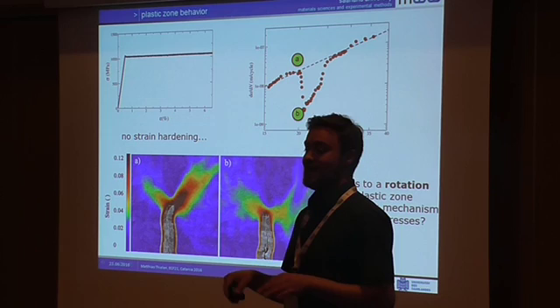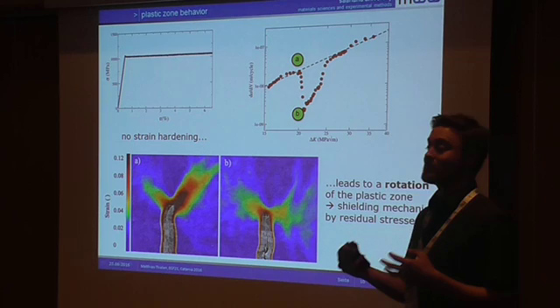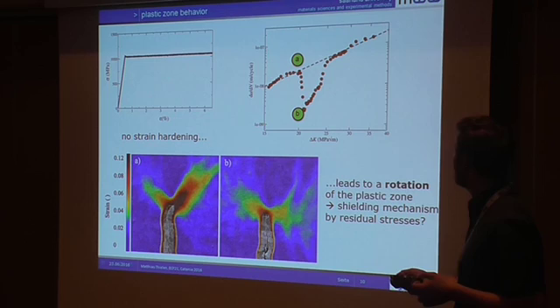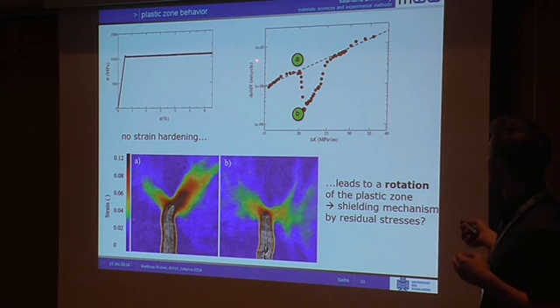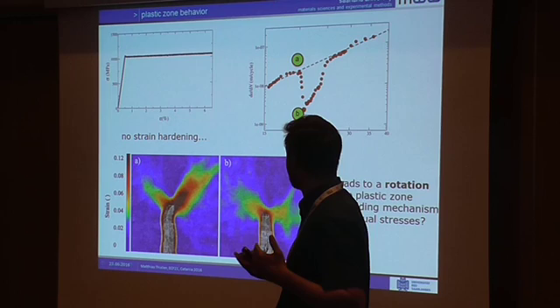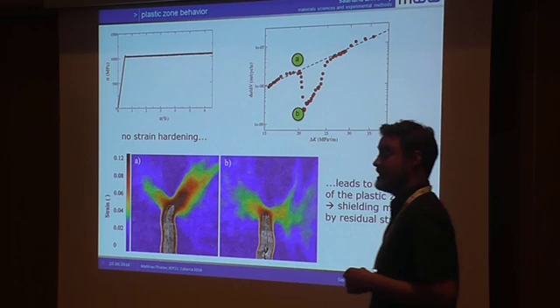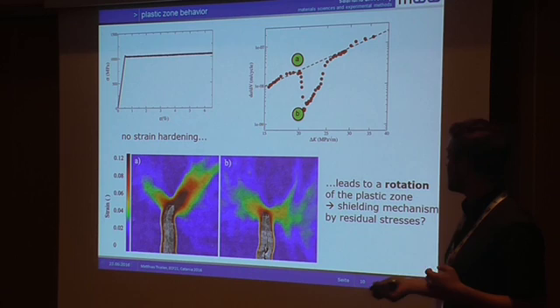If you want to describe material behavior, you start with a simple case — a material that doesn't show any strain hardening behavior. What you would have seen in the video is we let the crack grow to a certain point, then put it into our scanning electron microscope with a small tensile tester. We open the crack, match the displacement fields with digital image correlation, and derive the stress fields. Then we take the sample out of the SEM, perform the overload, fatigue again until it reaches its maximum retardation, and repeat this test to examine the plastic zone size.